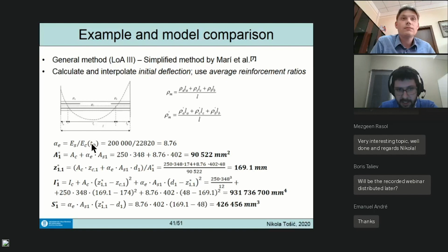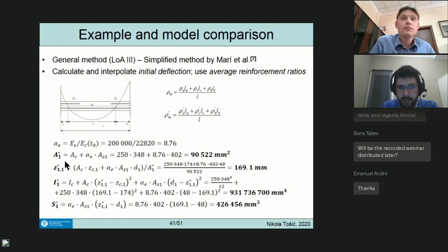Okay, so since you're doing the initial deflection, you take the ratio of moduli at this time, T0, which is now 8.76, not 23.7. And you calculate the area of reinforcement. Now it's different because this modulus ratio is smaller, so it's not 96,000, it's 90,000, and all the values are a bit smaller because the ratio of moduli is smaller. But you're doing it in state 1 and state 2, okay?